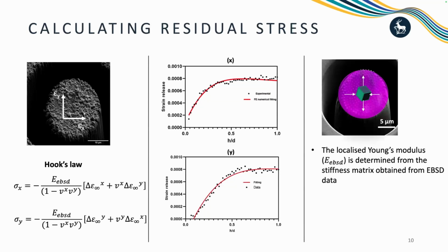Because copper and tungsten have a relatively large grain size, the milled pillar size is not large enough to get the bulk properties. So in this case, we apply EBSD to measure the grain orientation in this measurement area, and we calculate the anisotropic Young's modulus and the Poisson ratio, and apply those to Hooke's law to calculate the localized residual stress distribution in the different directions.